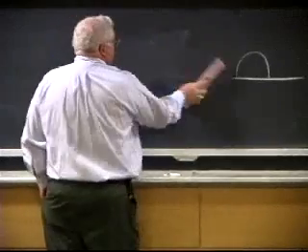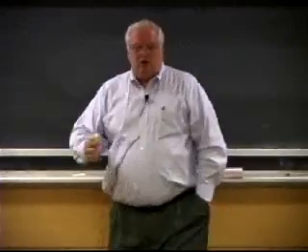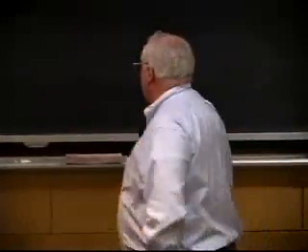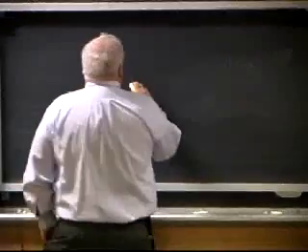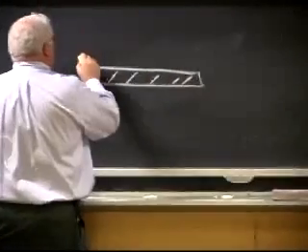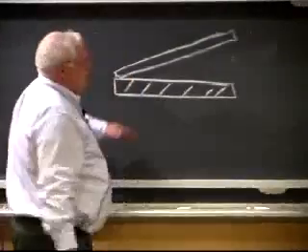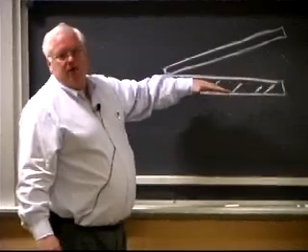Now, since we're on cold welding, I could talk about explosive bonding. Explosive bonding was discovered basically in World War II. There would be some explosions and people would look at the damage afterwards, and they noticed some things had just been welded together. Pieces of metal got welded together in the explosion. After World War II, people learned you could take a big heavy plate and put another plate at a critical angle, and the angle might be 10 or 15 degrees. It depends on what the two materials are, because we use this to clad other materials.